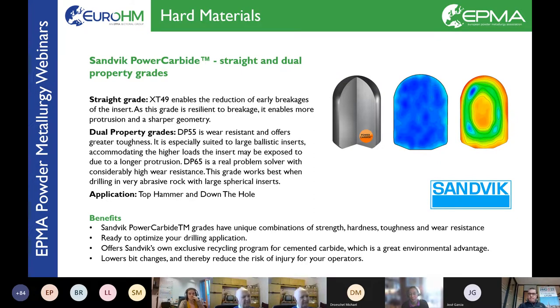You heard José García mention gradients in metal cutting before, and those gradients are typically 25 microns. If we look at the gradients in these materials, they are in the size of millimeters. So the core of this carbide is actually containing interface and tungsten carbide and binder. And the outermost part of the rock drill button is containing only tungsten carbide and cobalt.